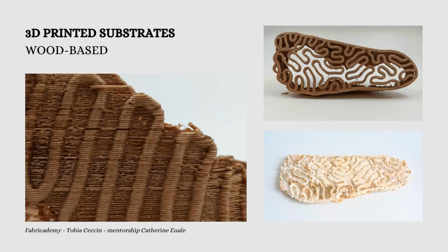So one trick for these, particularly for this wood one, is to actually dehydrate it before you use it. You can put it in the oven for a little bit and then allow some of the water content to leave. Then you can print it out, because that is what's making it more tacky, is that sometimes it absorbs water. That's really what it's made for. It's made for absorbing water and humidity, and that's why the mycelium can grow through it, because it's wood based, first of all, but also because it can hold humidity.